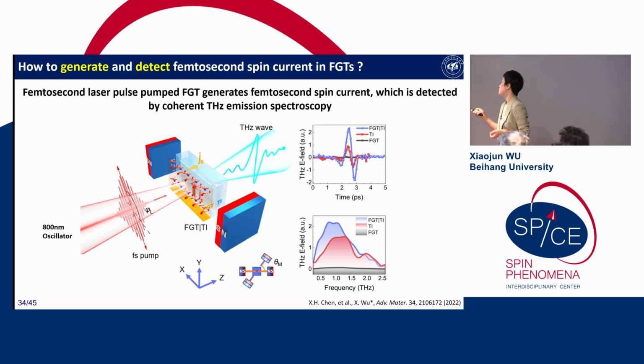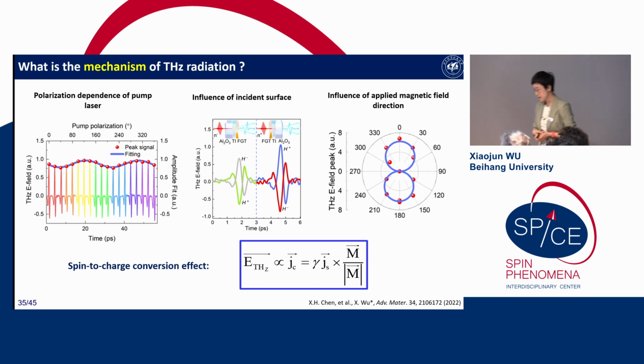The result is shown here, and this is the signal from the heterostructure. This is from the topological insulator. There is no terahertz from the pure iron germanium telluride. And so here we have something from the topological insulator, and we have to get rid of it. The first thing we do is the pump laser polarization dependence of the terahertz signal, and you can find the periodic signal here. So that is from the topological insulator.